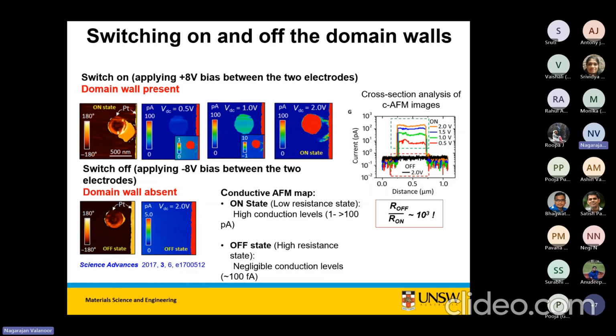So this was, I was really shocked at kind of how well this idea worked, you know. I think I've been in this business long enough that I know that if you have an idea and it works, then something must be wrong. So, and when the wall is not there, absolutely no conduction, no current over there. So we do the cross sections. And our on-off ratio is reasonably good. It's about 1,000. So for a prototype device, it's pretty good.